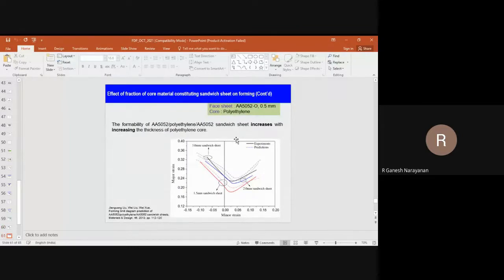Now, this example will tell you how forming limit changes with thickness. You can see A5052, 5 series, is combined with polyethylene. Polyethylene is a polymer core, and they are bonded by adhesive, let us say. The formability of this particular sandwich sheet increases with increase in the thickness of polyethylene core. That means for the same forming limit, you will see that a 3 mm sandwich has got better forming as compared to 1.5 mm sandwich, and 2 mm sandwich is in between. And you also know that sandwich sheet is also used for lightweight applications. And if you use this type of combination of materials, and if you change the thickness of the polyethylene core, it is said that formability can improve.